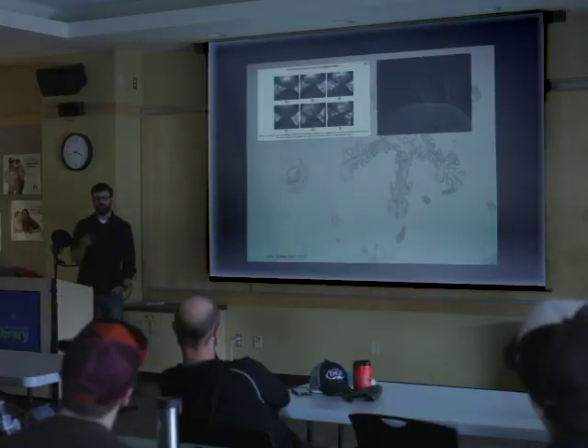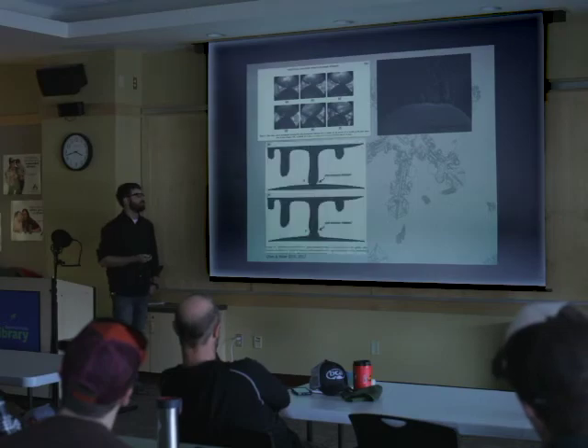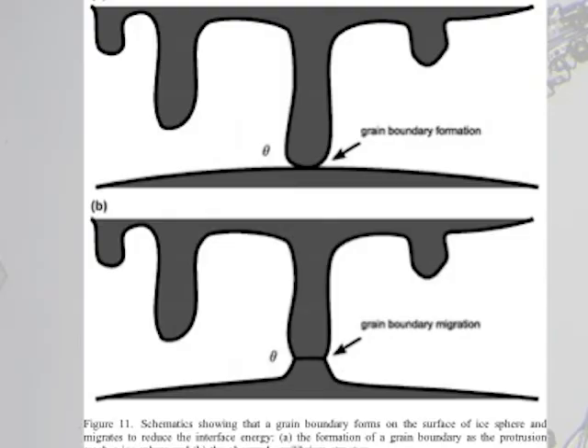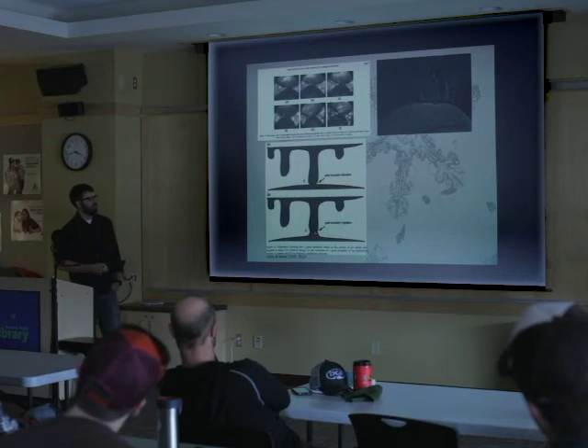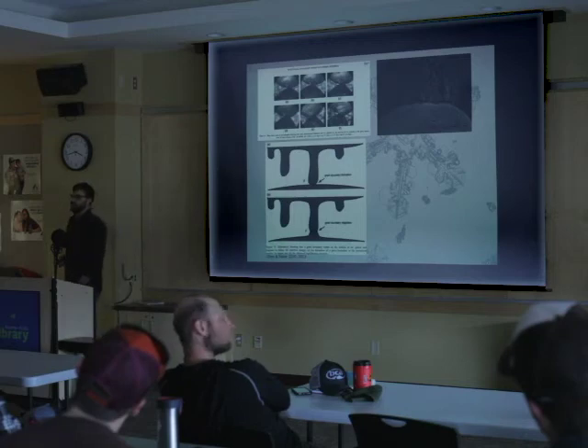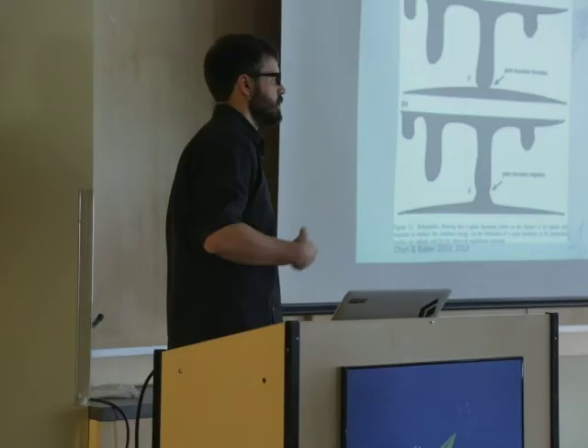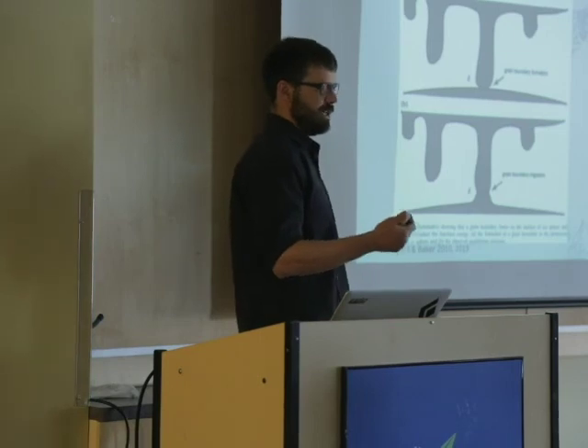Here's another image. This is a scanning electron microscope image of the same sort of thing. And what you see is that there's actually a number of different fingers that come down from one grain to another as these two ice spheres are bonding together. So this is what you need to break for fracture to really happen and for avalanche release. And another way to look at that, maybe more clearly in a schematic fashion, is that you might start with a grain boundary formation here between these two, let's call these snow grains, and how that boundary can actually move over time. It's not stationary. And one of the things I really feel like I say a lot in any of these talks I give about ice and snow is that snow is, number one, just ice with a lot of air in it.